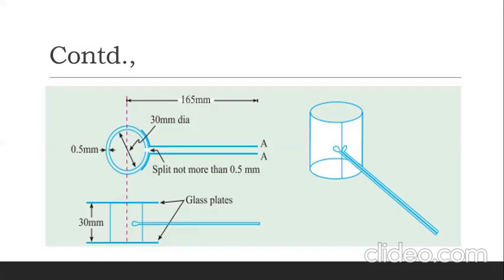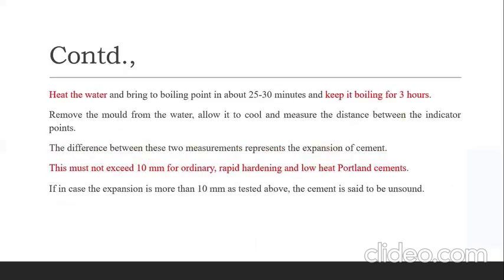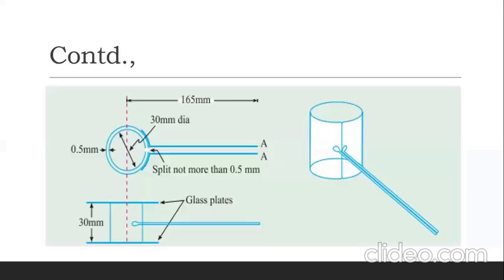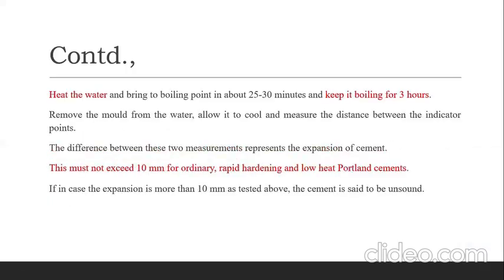I mean the container which is full of water, and at the same time you have to start heating the water. Within 25 to 30 minutes it has to reach the boiling point, that is 100 degrees Celsius, and the temperature has to be maintained for about 3 hours. After which you have to take the sample out, cool it, and check how much the needle has extended. Previously the needle will be closely spaced, whereas after boiling the water, the cement tends to expand in volume, and after taking it out from the boiling water, you can check the expansion of the needle.